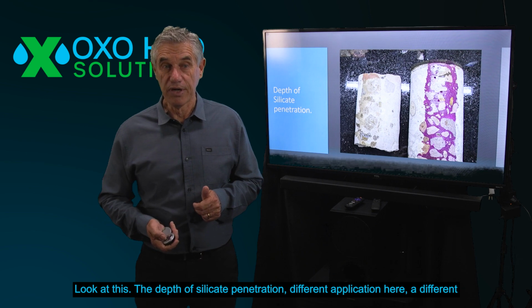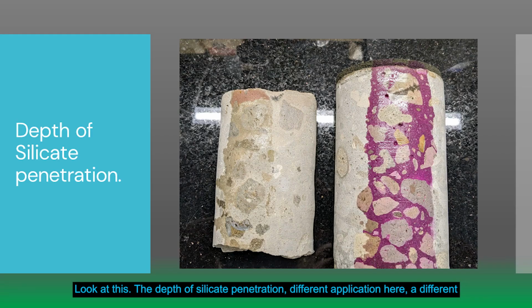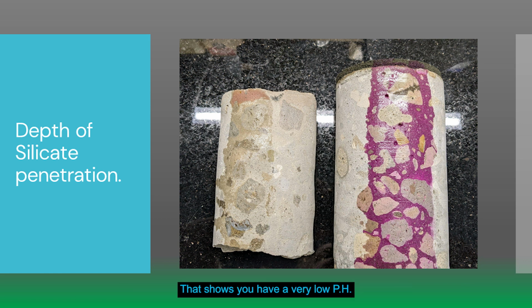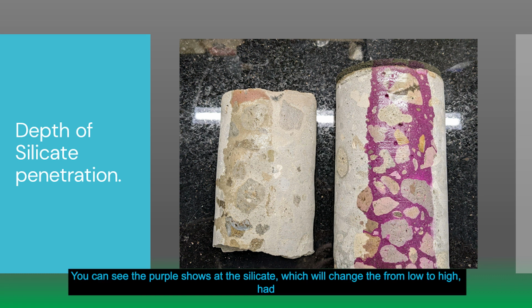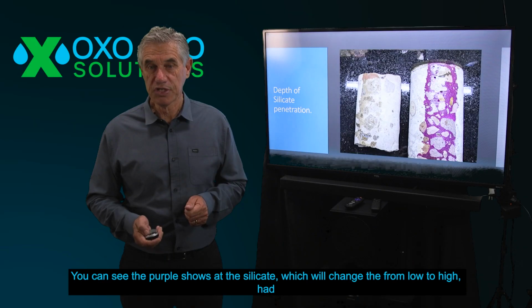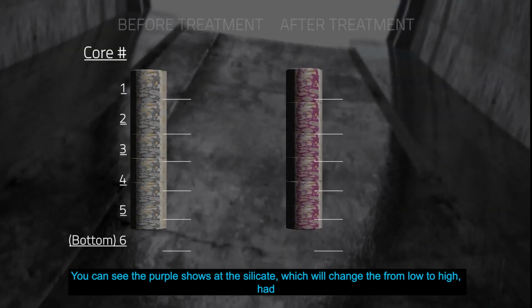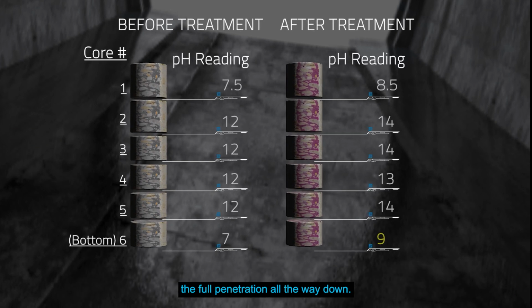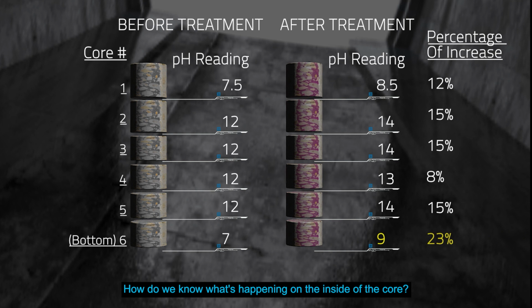Let's take a better look at this, the depth of silicate penetration. There's a different application here, a different facility. The one core on the left basically had no purple. That shows you had a very low pH. After it was treated, I believe this was an 8-inch core. Full penetration, you can see the purple shows that the silicate, which will change the pH from low to high, had the full penetration all the way down. Now, that's on the outside of the core.